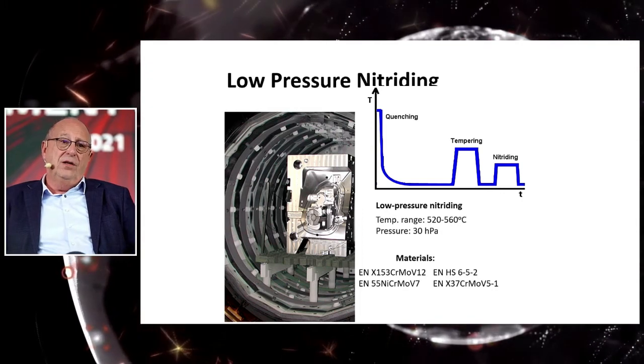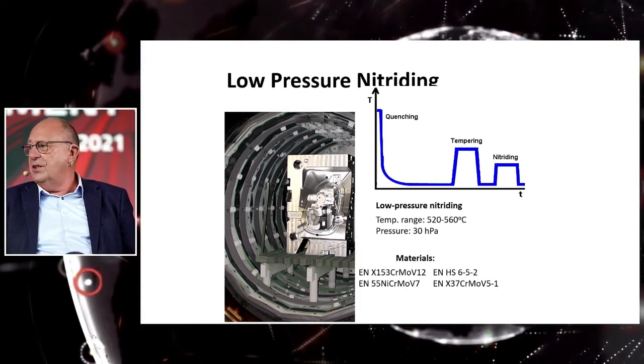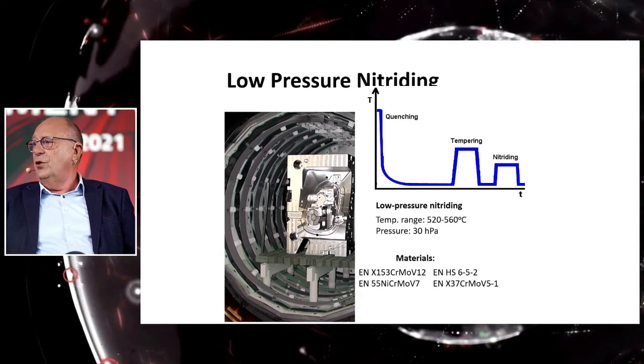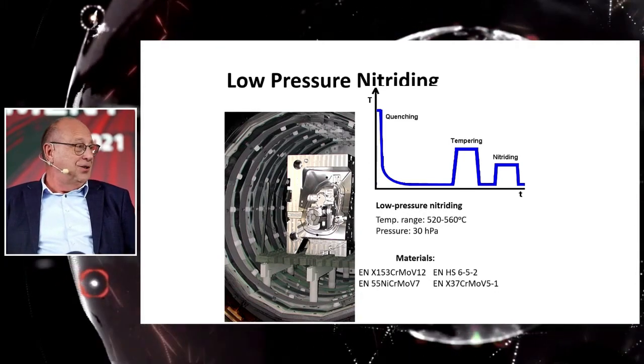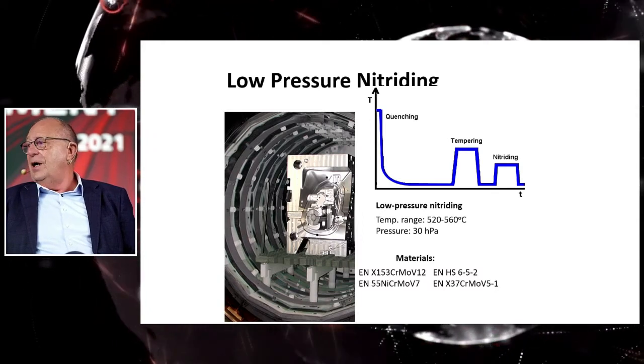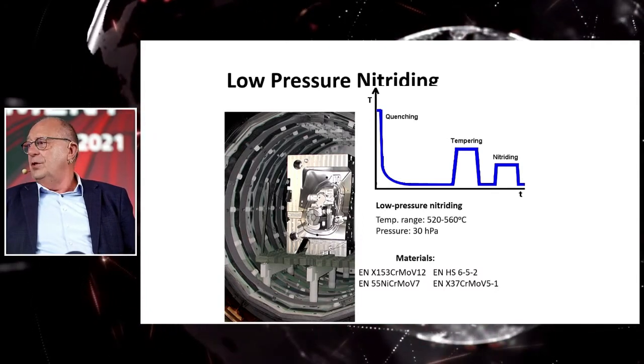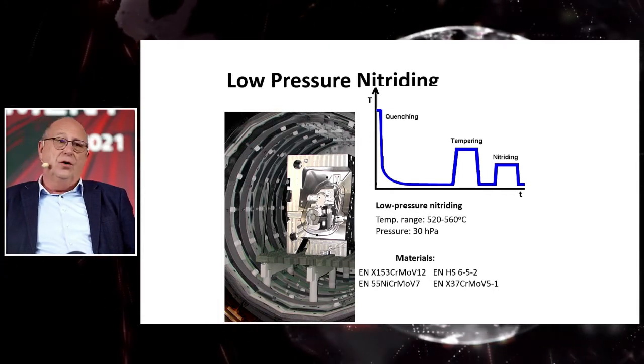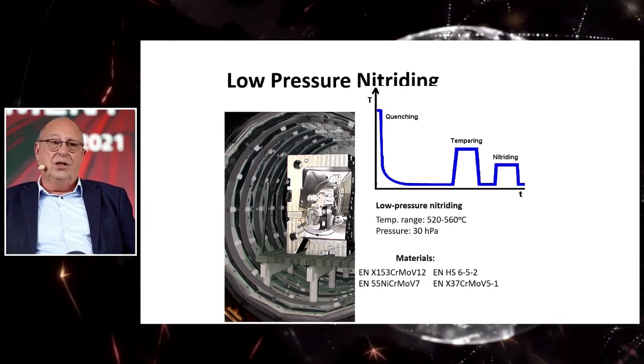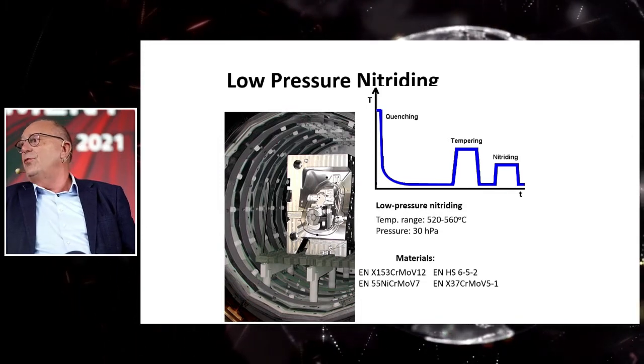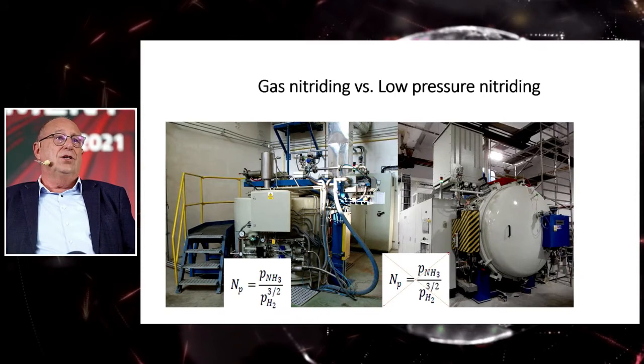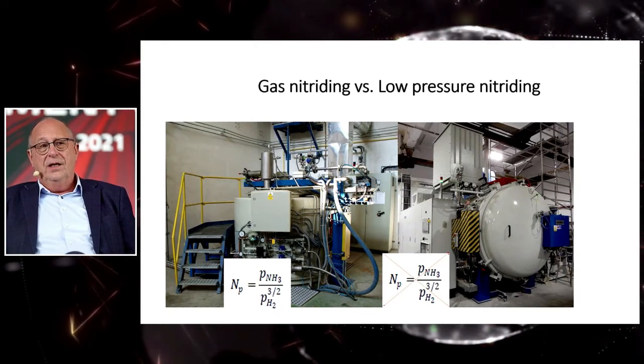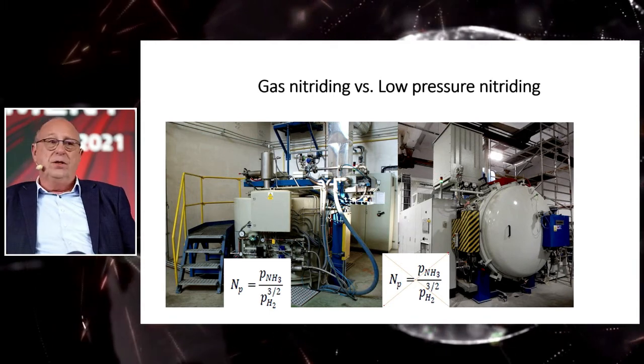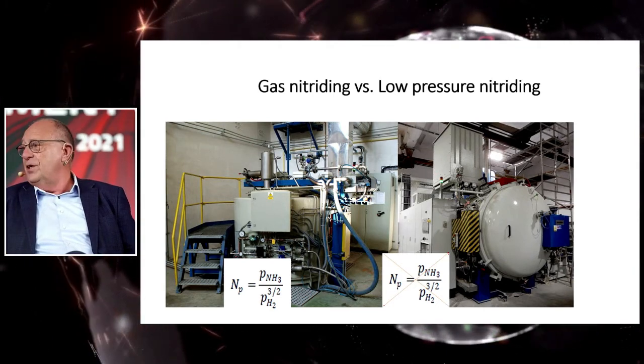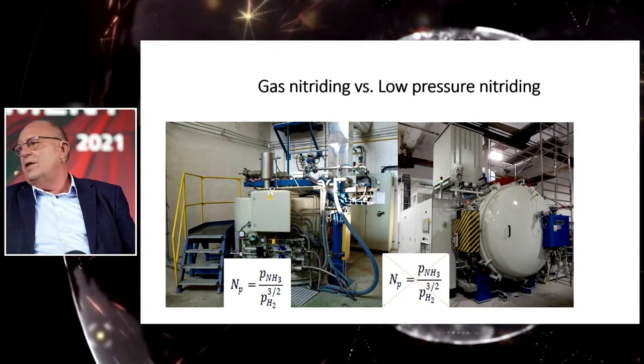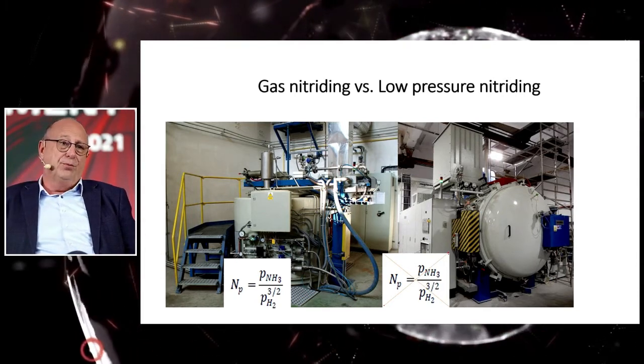And together with our team, especially together with Professor Korecka, we developed the CLPN software, that help us to foresee the proper parameters to reach the necessary microstructure of nitrided layer in the surface, especially the nitrided layers free of white nitride zone. So, of course, this program also was the great challenge, because also in this case the nitrogen potential widely used for the nitriding technology is further not descriptive for that process.